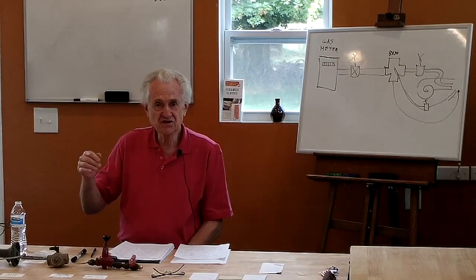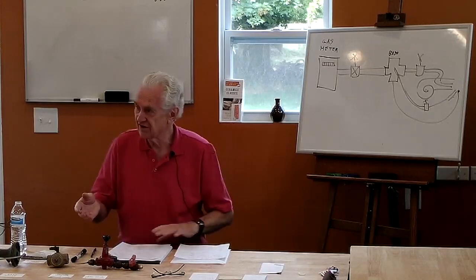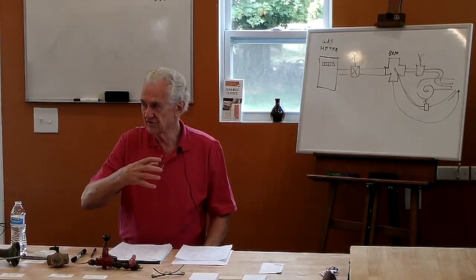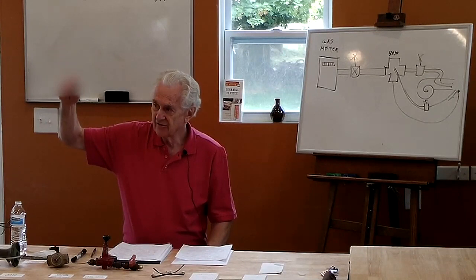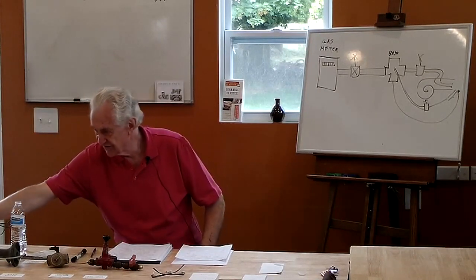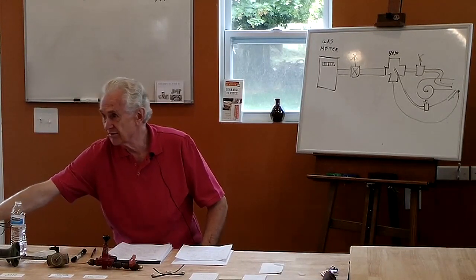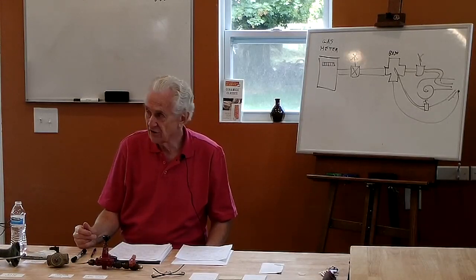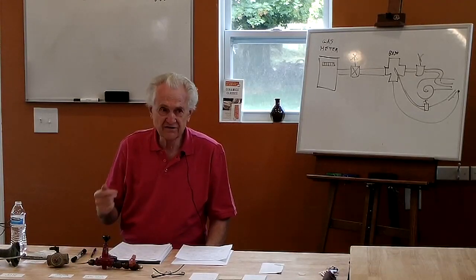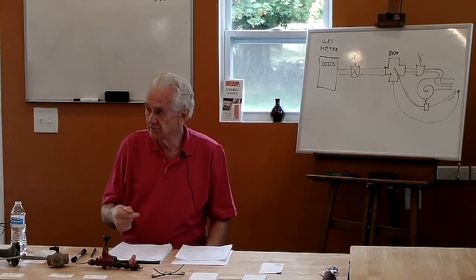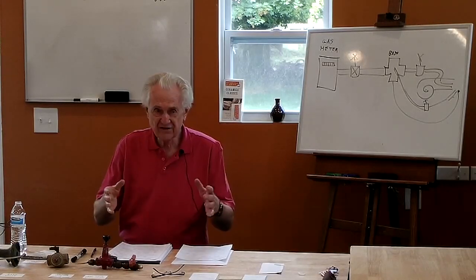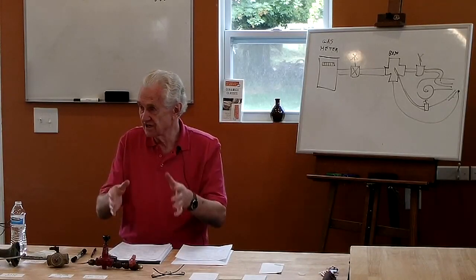And what happens is the chimney has the same function as the fireplace. The exhaust gases from the kiln go up the chimney, and they create a draft, and they pull in the secondary air that I need to burn with all the gas. So for cross-draft and downdraft kilns, I need a chimney. For an updraft kiln, I don't, because the kiln itself is functioning like a chimney.